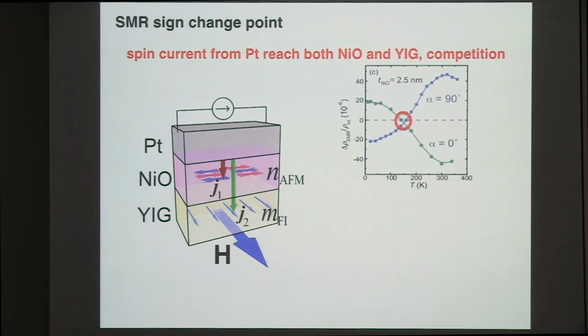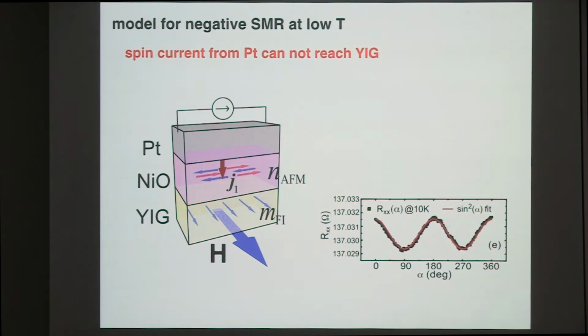Is there no exchange coupling between YIG and nickel oxide that makes both moments parallel to each other? I think for this case, we believe it's perpendicular. And of course, you can argue maybe it's parallel, but if it's parallel, we don't have this kind of thing. I can criticize myself like this: if you don't have hard evidence to show this perpendicular, basically everything is just a fantasy, right? So actually, we're preparing a single crystalline structure to verify this in the end.